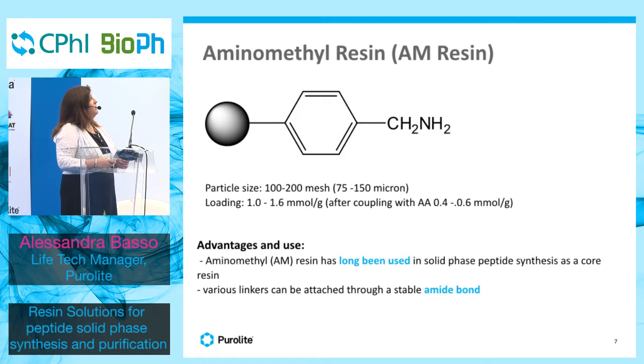The other resin is the aminomethyl resin, with the same chemical backbone, styrene divinyl benzene, with amino groups introduced after functionalization with the chlorine. The aminomethyl resin has a long history in peptide synthesis as a core resin for further functionalization with linkers, because after you couple the amino groups with the linker, you create an amide bond, which is really, really stable.